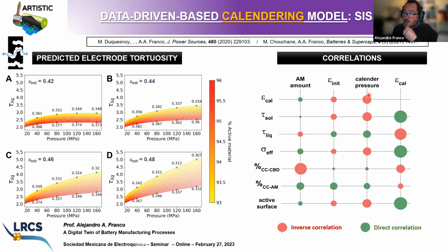If you take the example, for instance, of the calendering pressure, if you increase the calendering pressure, the porosity of the electrode decreases, and the correlation is very strong. So if you increase the calendering pressure, you also increase the tortuosity. The color here is green, and the correlation is quite strong. However, when you increase the calendering pressure, you see that you increase a little bit the surface area of contact between the carbon binder domain and the current collector, right? There is a correlation, which is a direct correlation, but the effect is weak, okay?